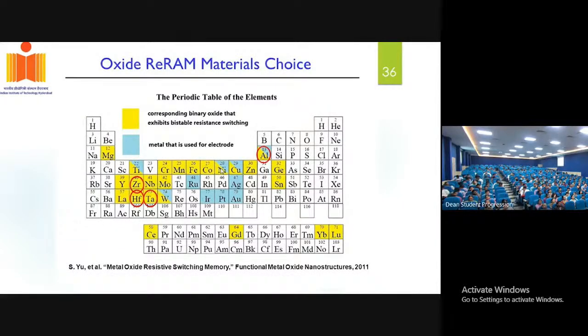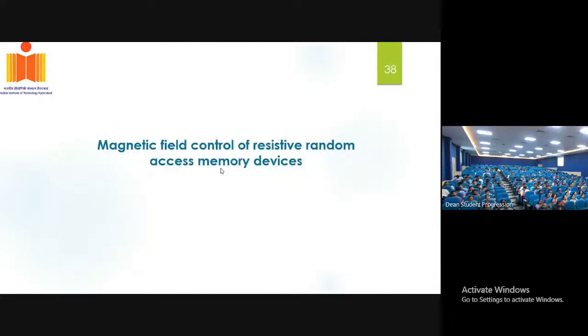There are various elements on which you can perform this resistive switching characteristic, but most prominently one would use transition metal oxide. In our laboratory, we have selected one of the important materials, titanium dioxide. Titanium dioxide is a very famous compound. We wanted to test for the first time whether we could tune the resistance state of the device with an external magnetic field. Remotely, we wanted to control the device without touching the device.